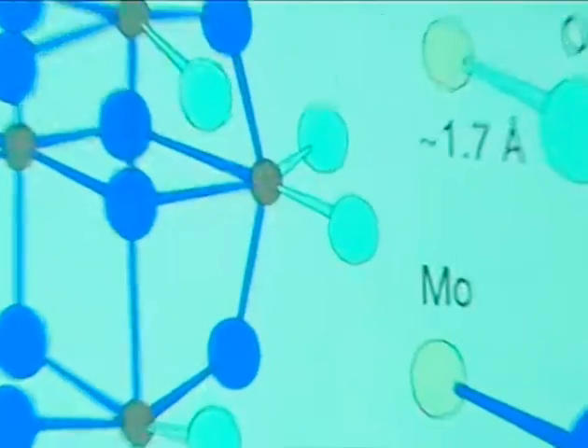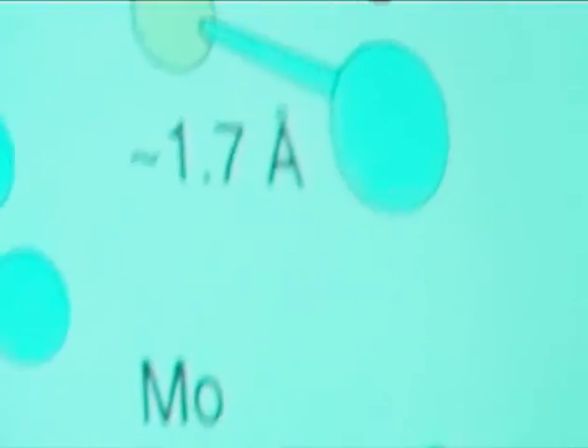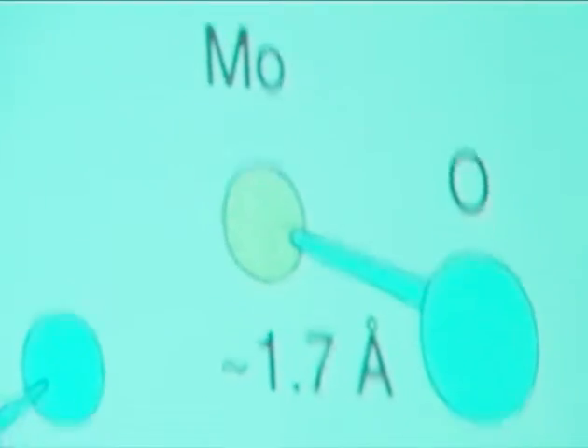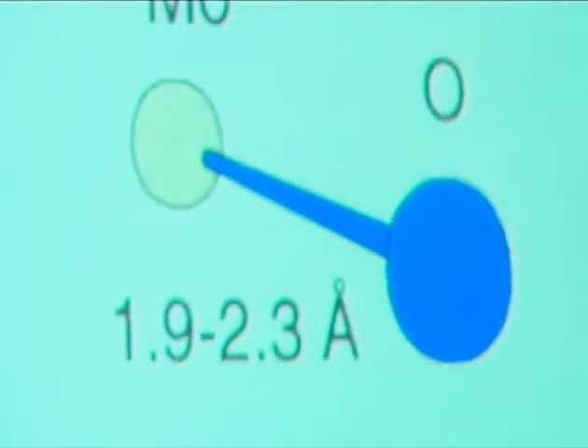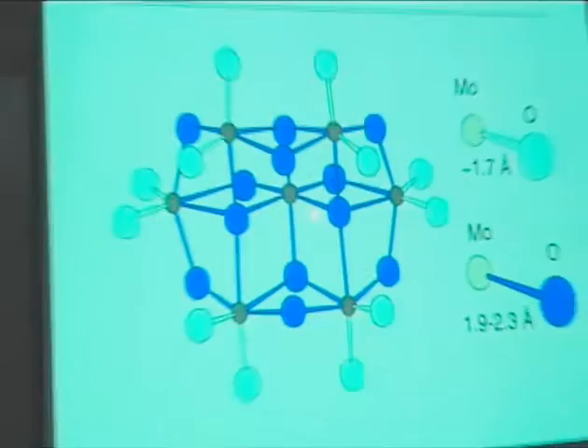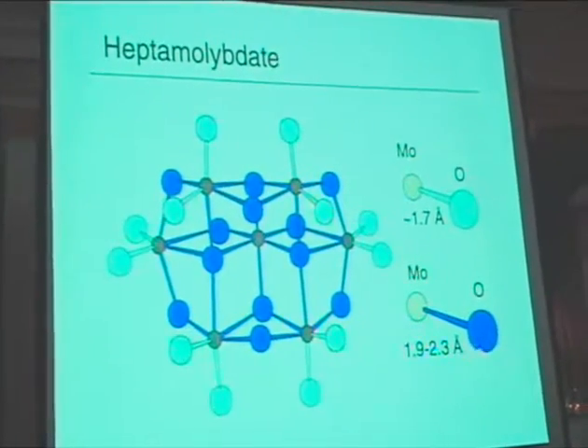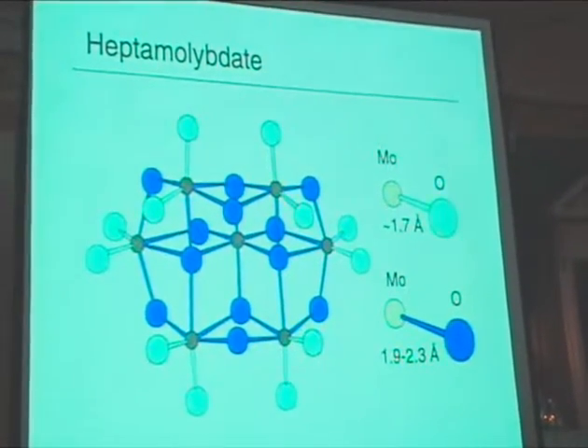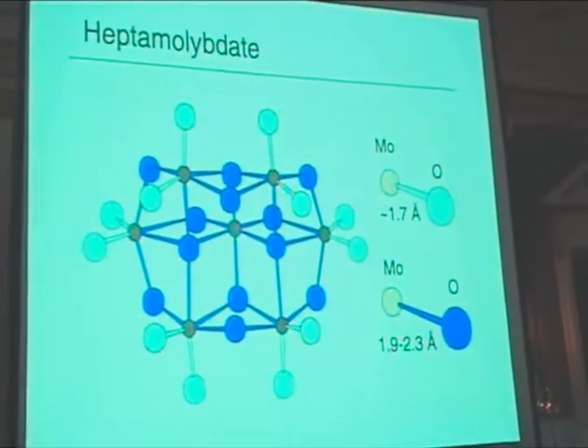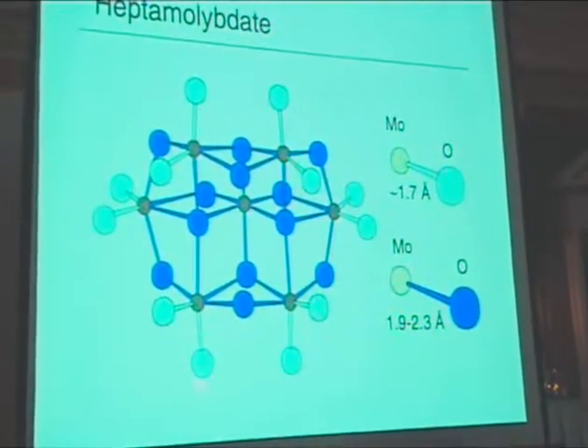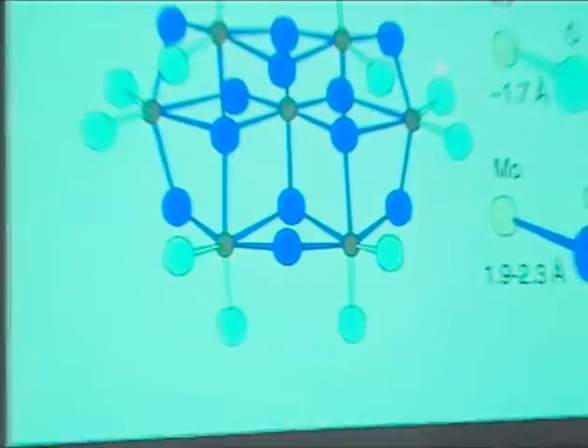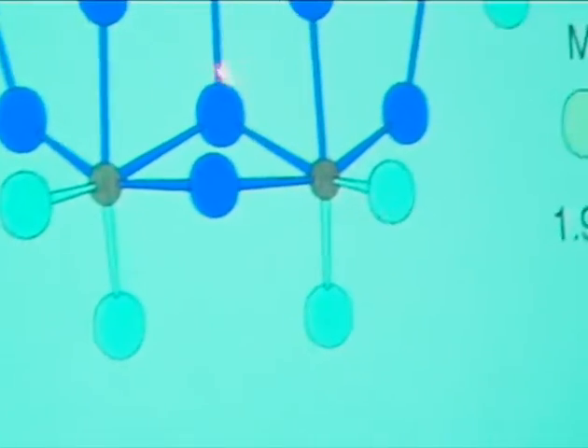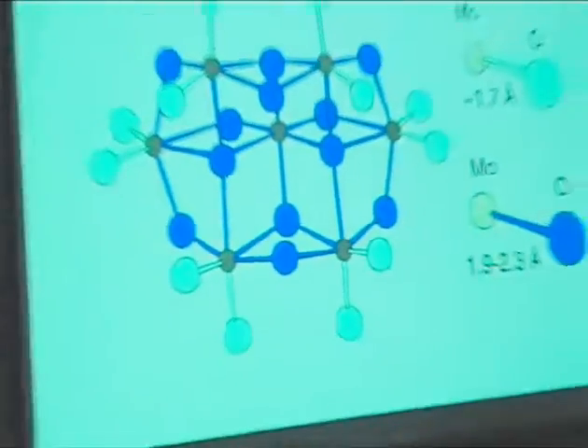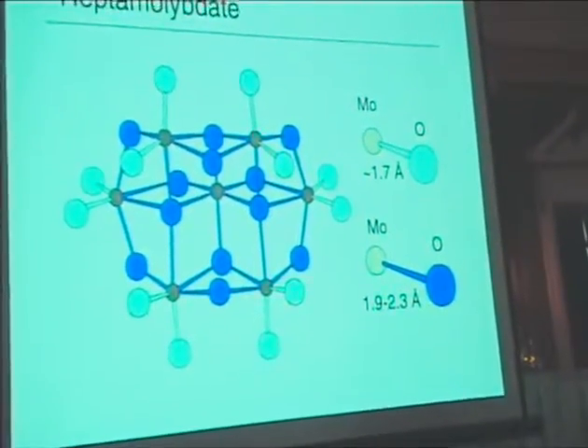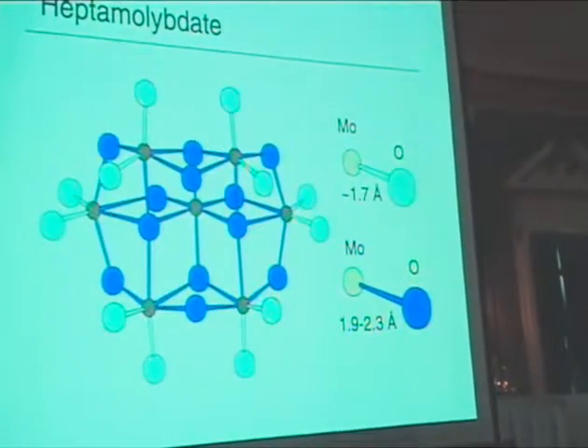So let's analyze that. We start with heptamolybdate. We all know the structure of heptamolybdate. It is 7 molybdenum, with a lot of oxygen. The internal oxygens, the molybdenum to oxygen distance, is long, and at the edge you get relaxation, so you get a contraction. The light blue is a shorter distance. Now the symmetry of the complex is low, so all the dark blue molybdenum distances are not all equal, and this is why you saw several peaks.